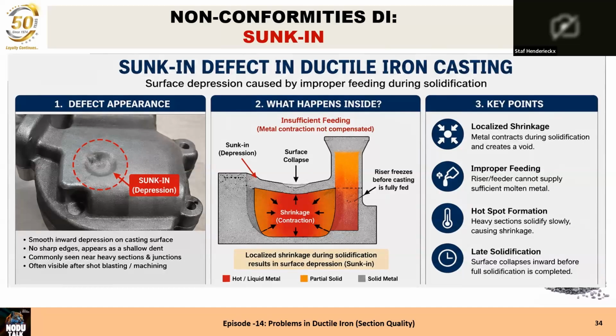And sometimes there is a machining stock, and due to the sunk in, the casting cannot be machined all over because there is too much machining stock in the center, and then the customer will also not accept it. It's a localized shrinkage. You need here that the metal in contact with the mold solidifies quickly, so that there is a thin layer of solidified metal, which later makes this sunk-in happen. It's about improper feeding, it's about hot spots, and it's again late solidification, but not as late as the micro shrinkage. It's in between the first solidification and the last solidification.